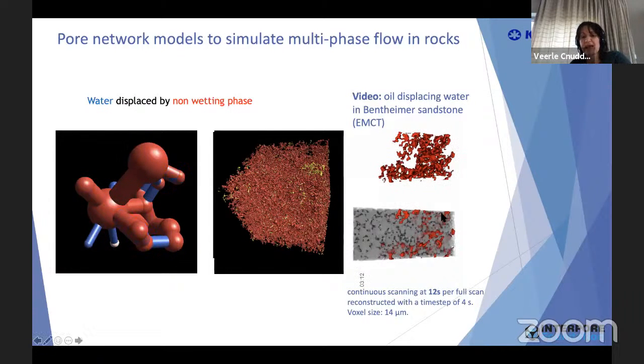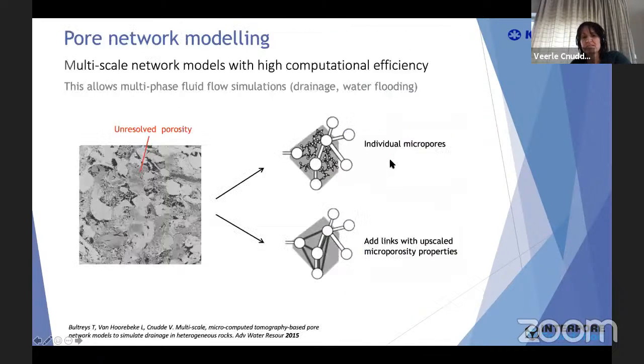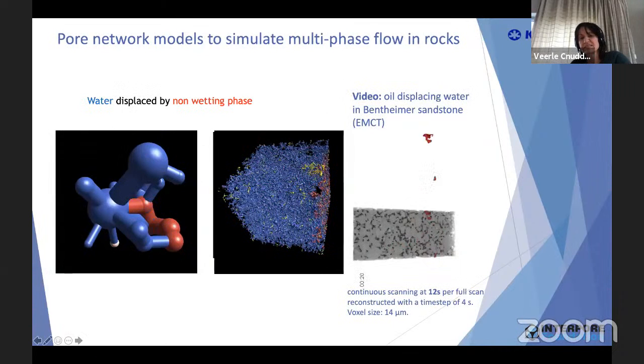So we have our sample, we have it fully water saturated. We made the water, in this case, virtually invisible, so you don't see the water now. And then we inject also the oil, which is displacing the water, and we are visualizing how this movement is happening. So, if I go one step back, now you see here, this is what we modeled, how the behavior would be. And this is then also reality of a very small part, of course. It's not completely a copy, but it's from a similar rock.